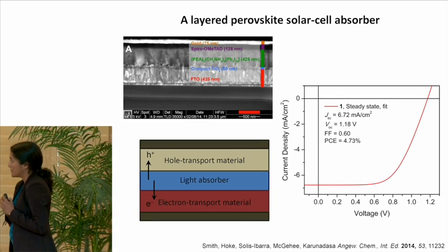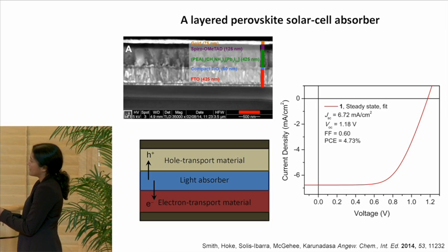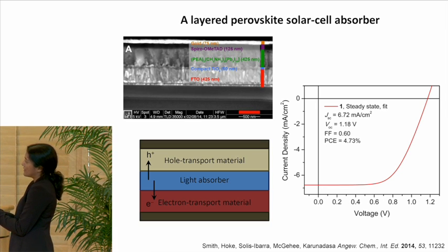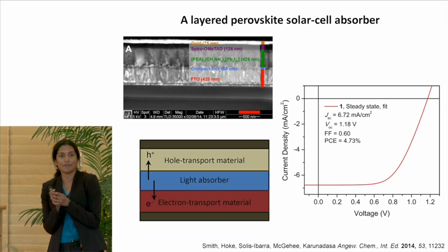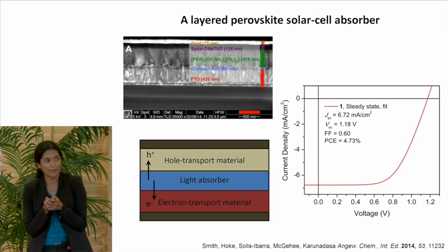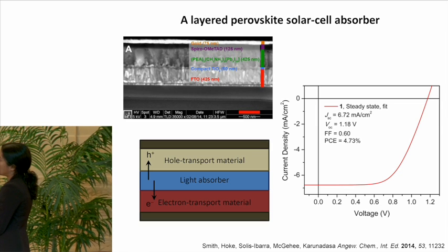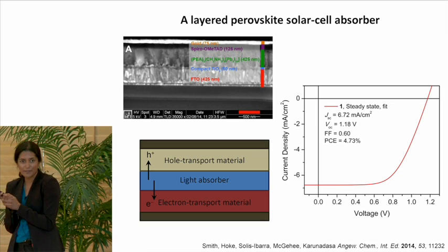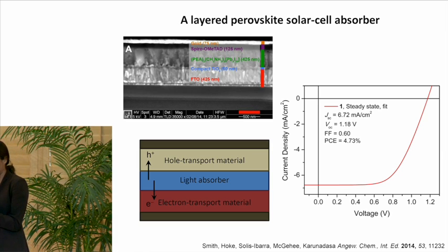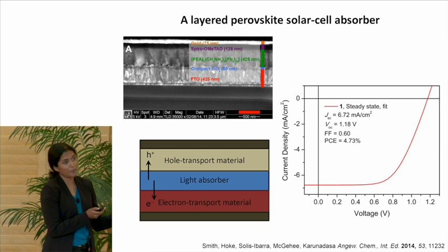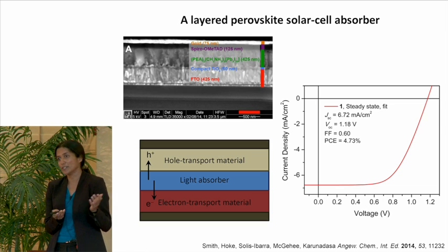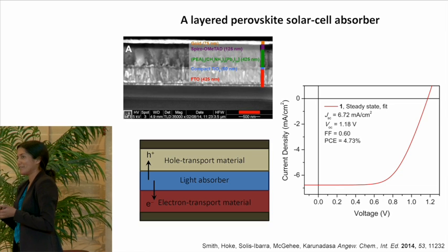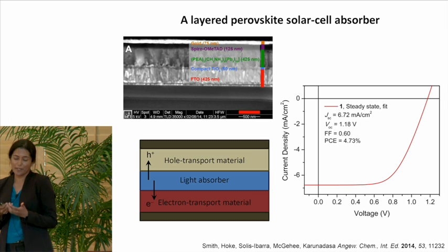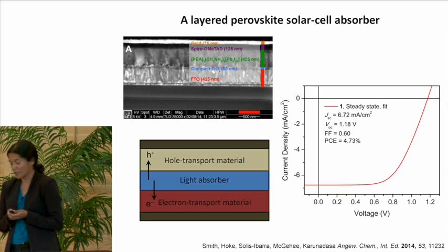So he constructed a planar geometry solar cell device where he basically used a flat layer of titania as the electron transport material, deposited the layered perovskite as the light absorber, and spun an organic hole transport material on top of that, and he found that this material does indeed work as a solar cell. Our first generation devices have power conversion efficiencies of about 4.7%. And this compared to the highest efficiencies with 3D perovskites, which have now reached about 18%, is a low number. But this is not an optimized device in any way. And I'd like to discuss some advantages of the 2D material with respect to the 3D structure.